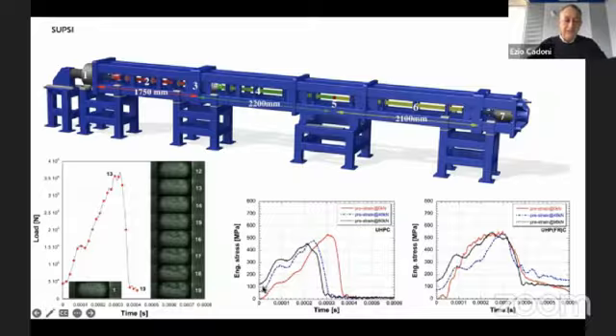All the tests have the same gradient up to the first 60 microseconds. Afterward, the stress versus time curve changes due to the presence of activated cracks during the preloading process. Activated cracks and the stress rate play a crucial role in nucleating the cracking process that results in specimen failure. The material had a more uniform response in tests with higher static preloading values, but its strength was lower caused by the quasi-static loading in case of UHPC, while the fiber-reinforced material does not present significant differences.